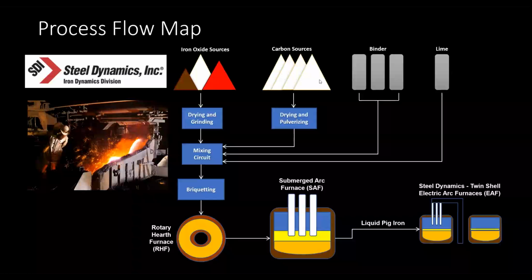All of these raw materials eventually end up in a mixing circuit. We have to dry and grind the iron ore products, dry and pulverize our carbon to get into the mixing circuit. Our binders are basically organic, sugars, things like that, and then lime all goes into this mixing circuit. We make a briquette—I don't know if it's standard to say, but our briquette going into the RHF kind of looks like a large water softener type salt.